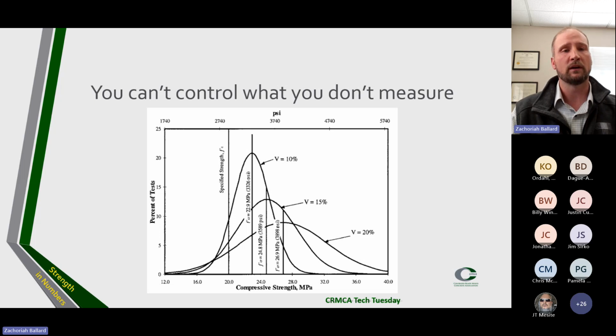So a higher coefficient of variation is going to give us a wider range of results. If we have a tighter coefficient of variation, then we have a narrower group of expected results. Each one of these curves on the screen here is shifted off to the right side of the curve, so our mix is designed for a higher strength than our specified strength. If we can dial our mixes in and our quality control on these mixes, we can actually start to push these to the left and closer to our specified strength. So now we can spend a little bit less on materials potentially.